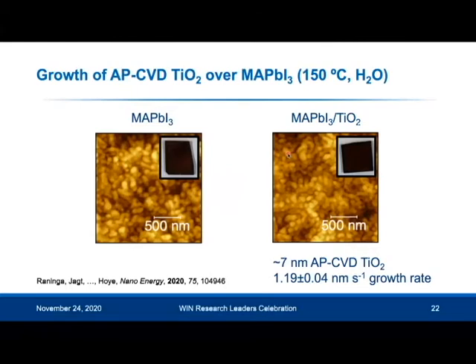But with this technique, we're growing 7 nanometers. And because the growth rate is several orders of magnitude higher than for ALD, we can keep the deposition time within a minute. And this, you can see, avoids visually changing the appearance of the perovskite, as well as avoiding any change to the morphology as well.